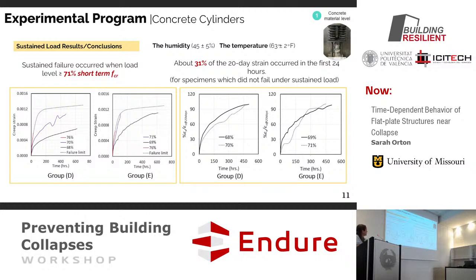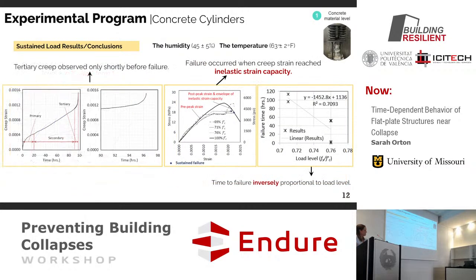But you can see this test here, 68% didn't reach failure. This one at 70% didn't reach failure. And this one at 76% reached failure. And this one at 71% reached failure. You can also look at the strain rate increase. About 31% of the 20-day strain occurred within the first 24 hours. And so it really is that primary creep where you get most of the strain effect very early on, and then it kind of slowly goes on there.